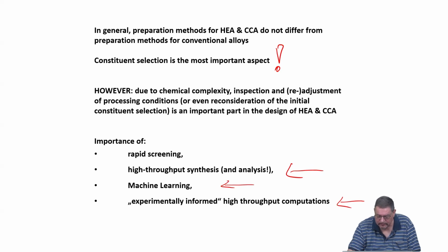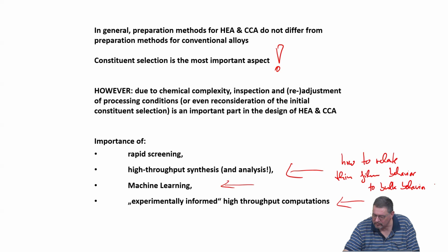The big issue here is how to relate thin film behavior to bulk behavior. This is not easy because you have additional stresses, you have a huge surface area, you have different diffusivities, you have maybe different quenching rates if you deposit the film, as compared to bulk processing. And so one has to be very careful there. This is done in abundance over the world, but I'm skeptical.